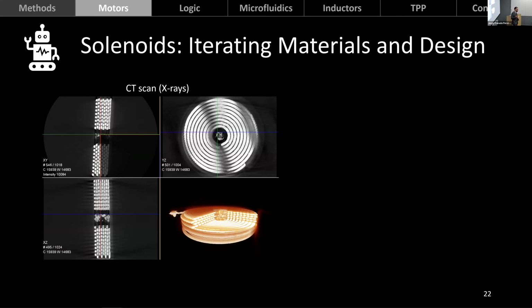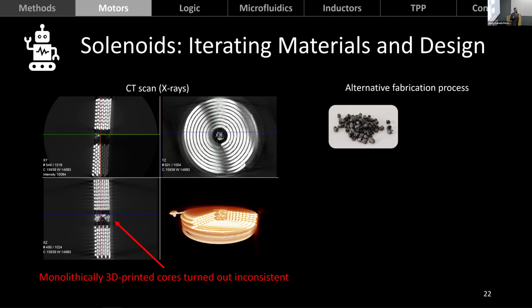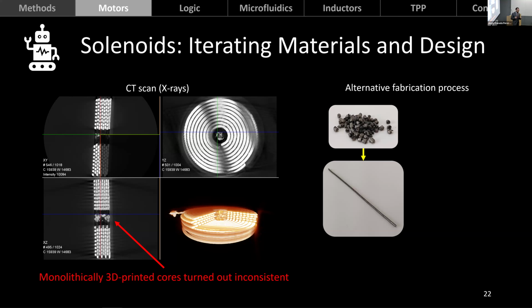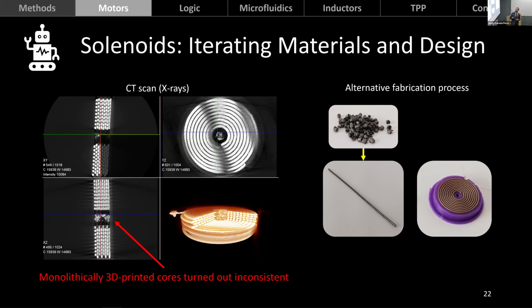And we imaged them in several ways, including CT scan or X-rays. And we noticed that the monolithically 3D printed cores that we were fabricating were not turning out fully dense, which is a problem because we probably wouldn't get the performance that we were expecting. So we came up with an alternative fabrication process to check this, in which we fabricate a bar of this magnetic material from which we can break pieces and make them into cores that we can then insert into 3D printed solenoids.